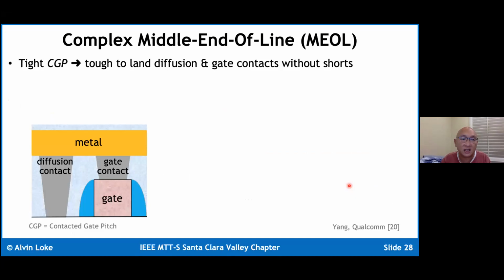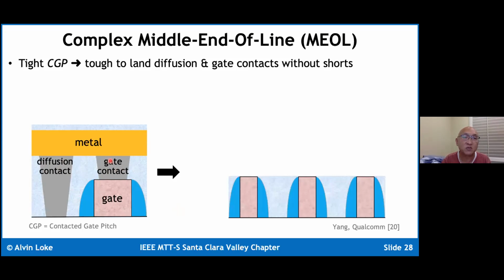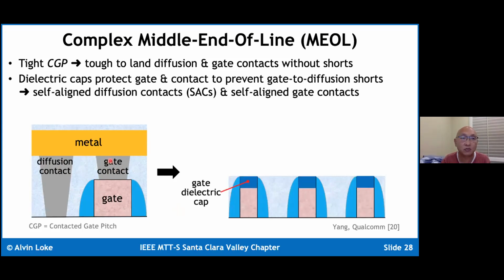Now, as we keep getting to tighter and tighter contact to gate pitch, it's inevitable that it's going to be tougher and tougher to land diffusion and gate contacts without the diffusion contact shorting to the gate contact. In 28 nanometers and earlier nodes, we were used to having only one mask for doing the diffusion contact as well as the gate contact. But as we've moved on to these advanced nodes, life is not that pretty. Basically, what has been required to land contacts into this contact module, which is sometimes referred to as the middle end of the line module, is to have self-aligned diffusion contacts and gate contacts.